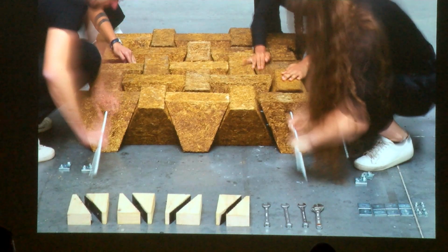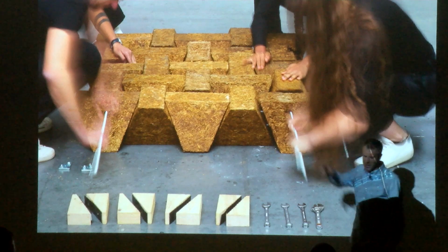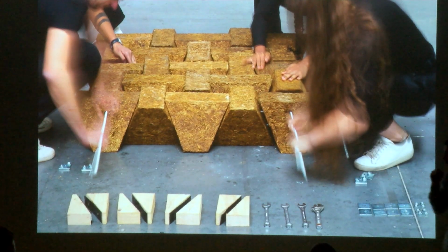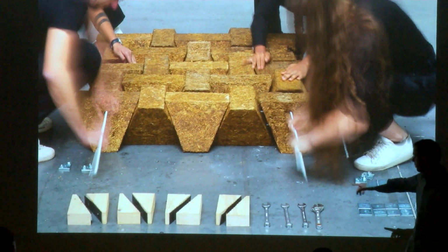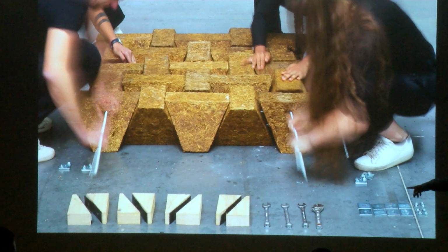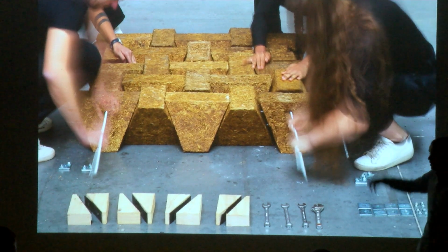This is a photo of the assembly, so as you can see, the metal rods are passing around the perimeter. We located 2 at different heights. Later on, we realized that probably 1 was enough, but for this initial prototype, we had 2 of them. The only thing that was required to assemble the whole slab was very basic tools, available in any location. And the beauty is that once the slab is not required, you can just unscrew it, disassemble it, and bring it somewhere else.